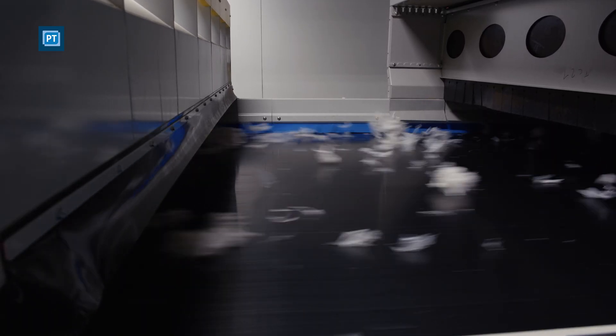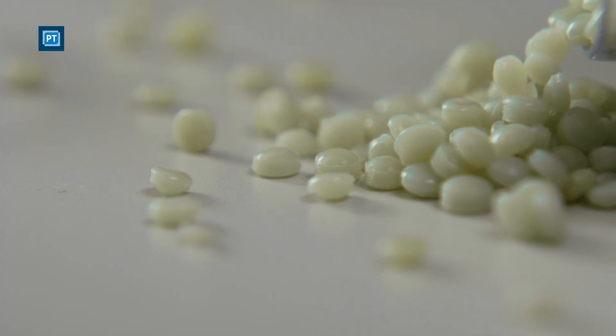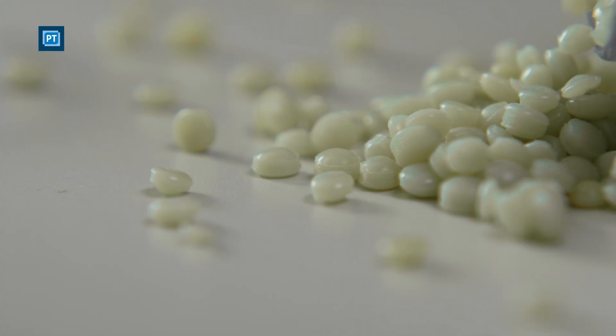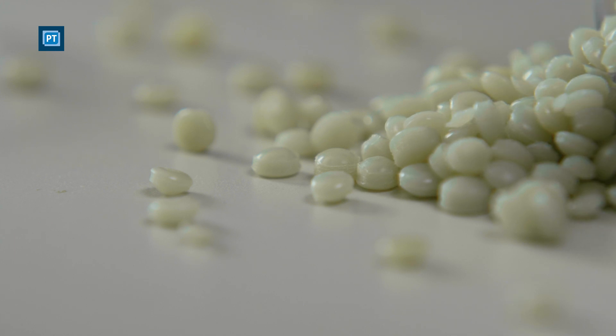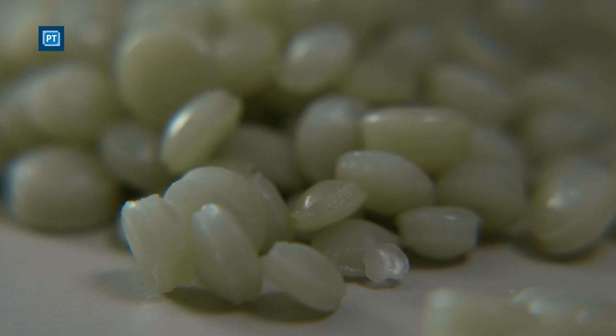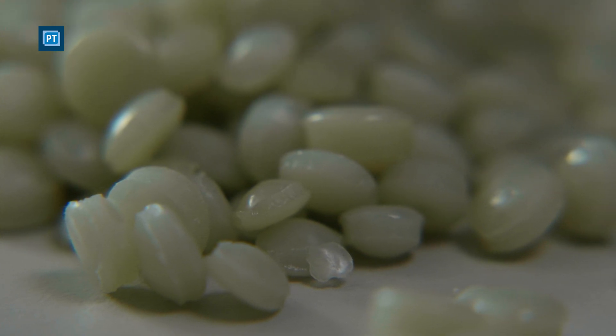The selected fraction — the really good, clean, clear polyethylene — goes on to a further shredding step, then it's washed, dried, and goes on to densification. Plastic film can't be fed directly into an extruder; it needs to be compacted first. This film is compacted, then goes into the extruder where it's melted, filtered, and turned into pellets.